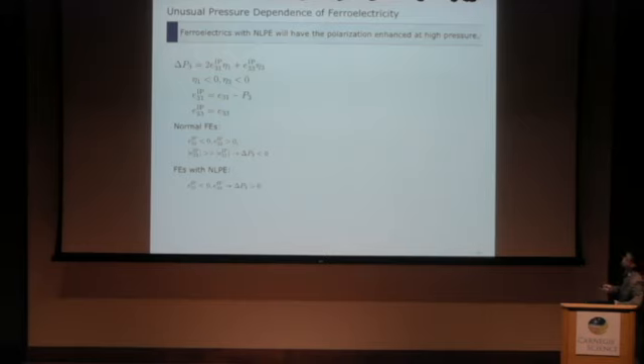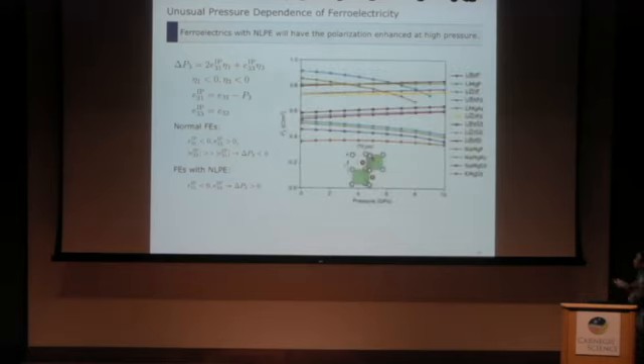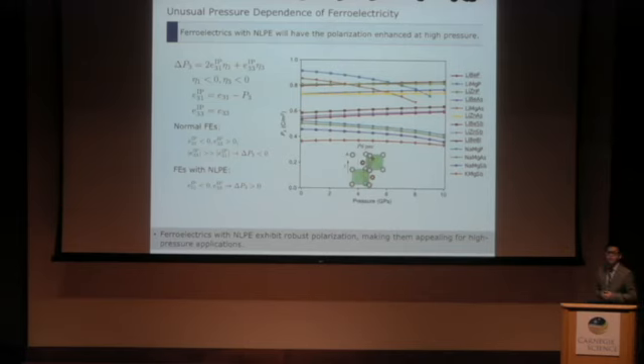For normal ferroelectrics, because of this very positive E33 term, the polarization change is negative. However, for ferroelectrics with negative piezoelectric coefficient, this will result in polarization enhancement. And this is indeed what we observed based on our DFT calculations. What I show here is the polarization change as a function of hydrostatic pressure. As you can see, a lot of them, particularly for ABC ferroelectrics with negative E33, have polarization increasing with increasing hydrostatic pressure. So this makes them very appealing for high-pressure applications.